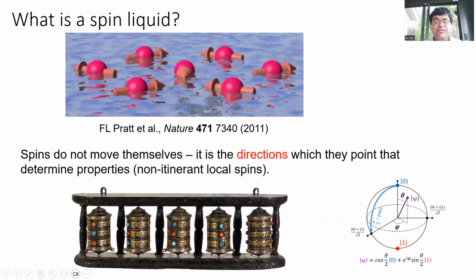So it's more like a Buddhist prayer wheel, which can rotate, but the position of the Buddhist prayer wheels doesn't change. So that's what it ultimately is. So it's the effective rotational degree of freedom, not the translational degree of freedom, which gives rise to this spin liquid character. And so what we also mean is that the spins are actually non-itinerant. So that's basically the point.